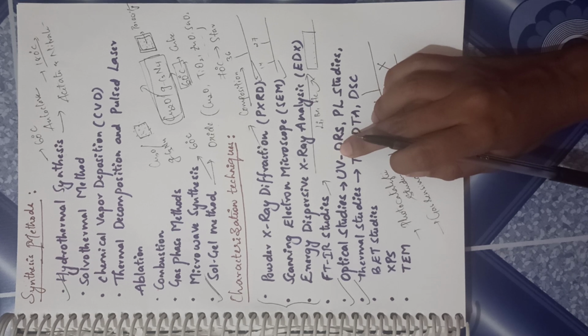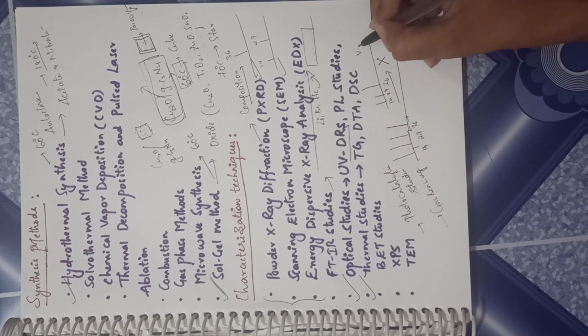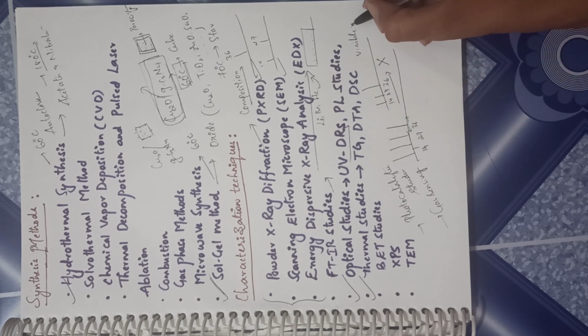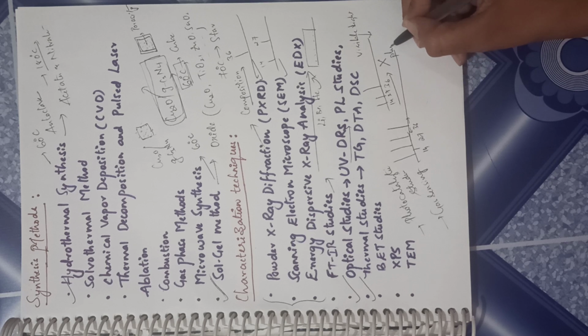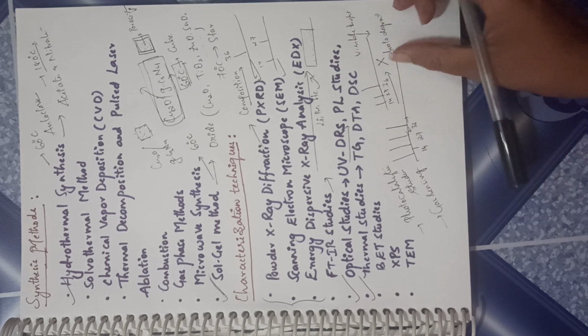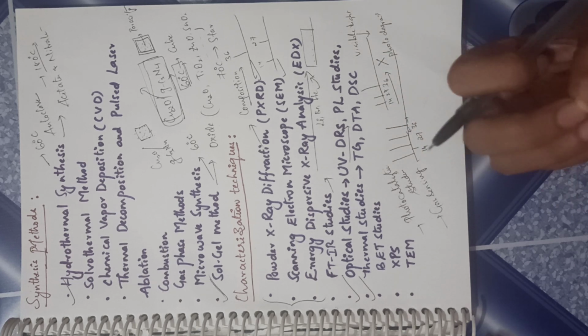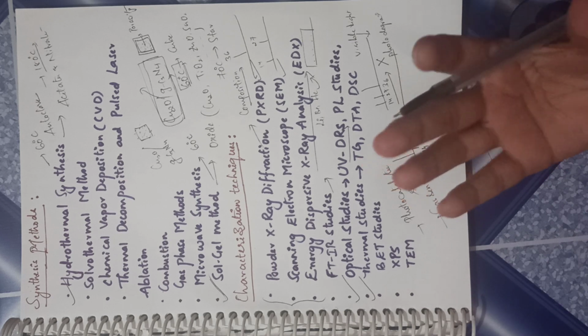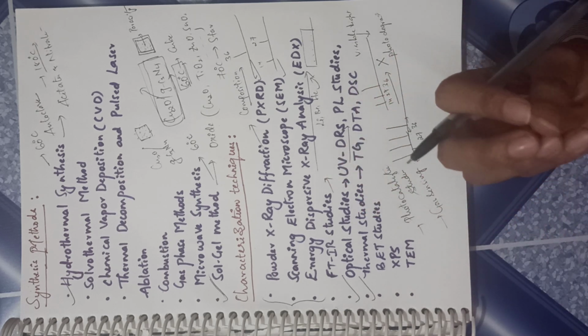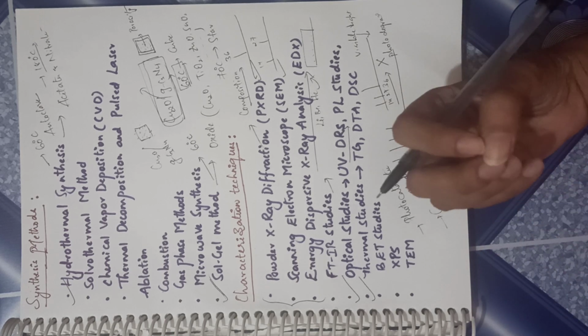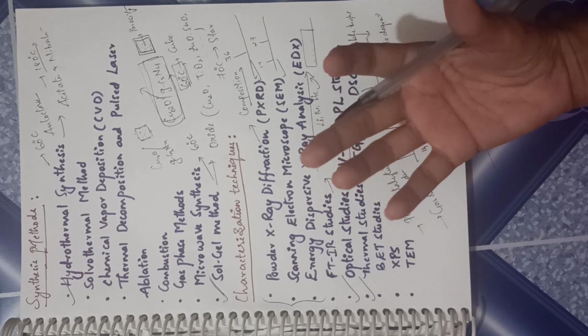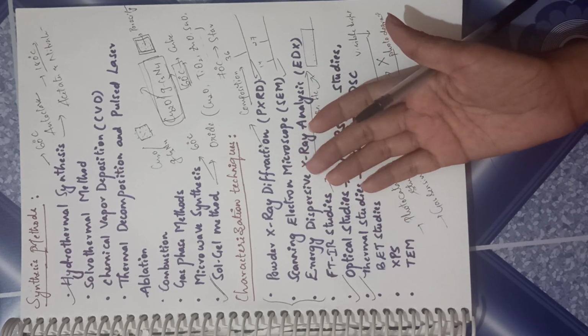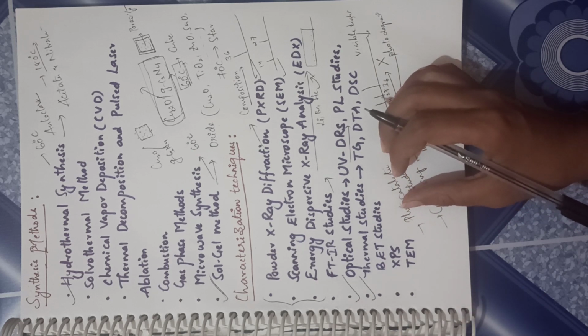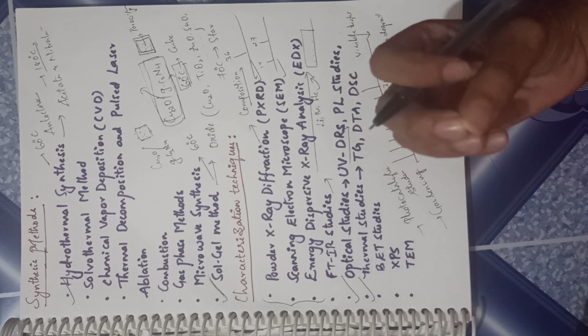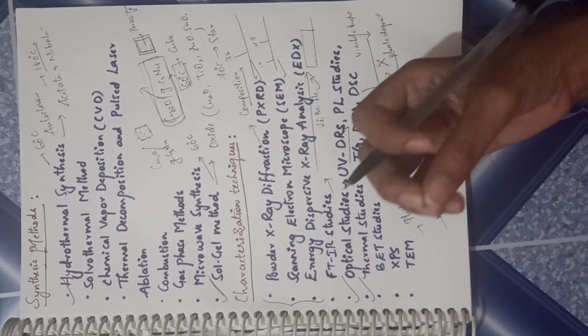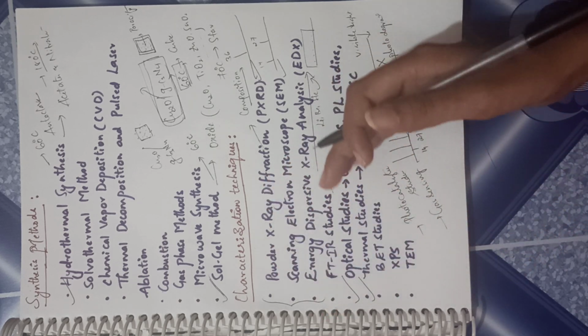This is done to find out the band gap of the material. Let's say if your band gap is in the visible light, which you determine using UV-DRS studies. So this is very helpful for the photodegradation studies. Okay, for the photodegradation studies, if you want to degrade some dye, it is always better if you have the light in the visible region, because the UV region is harmful and it is not a natural source available for us. The only natural source we have is the sun, which is visible light. So it is always better to get a band gap in the visible light. In the sense, if it is not in the visible region, you can fine tune it using doping or various other techniques to shift the band gap from the UV to the visible region and then perform the degradation studies.